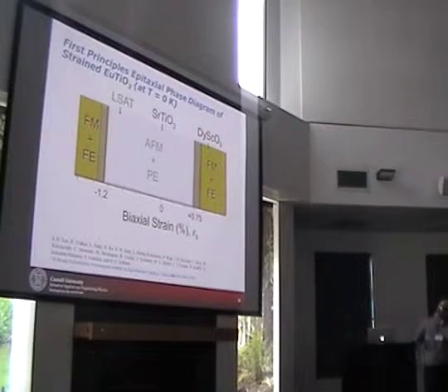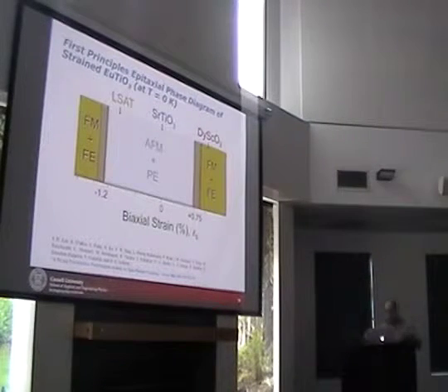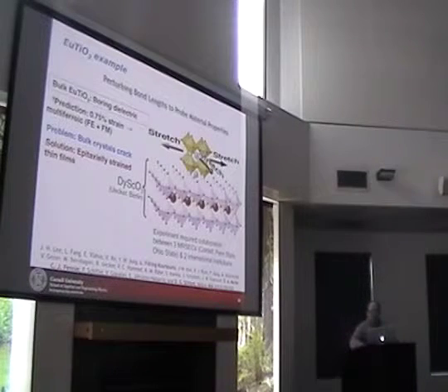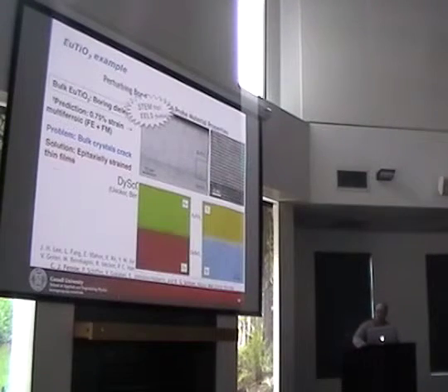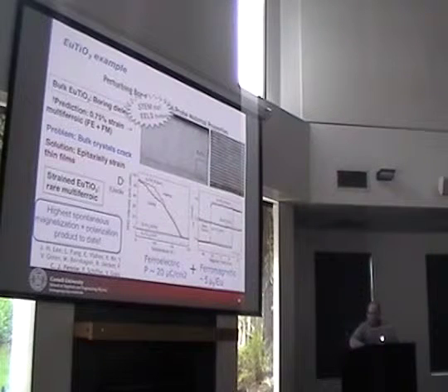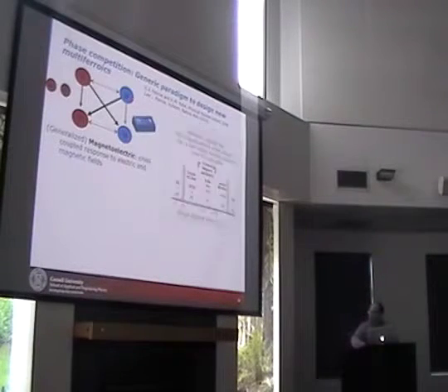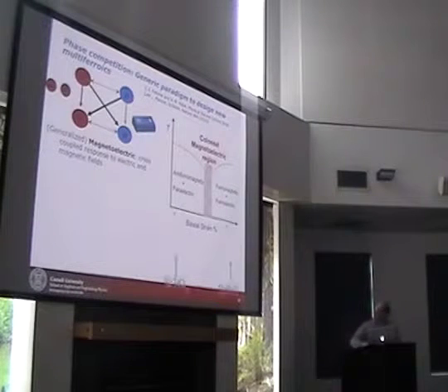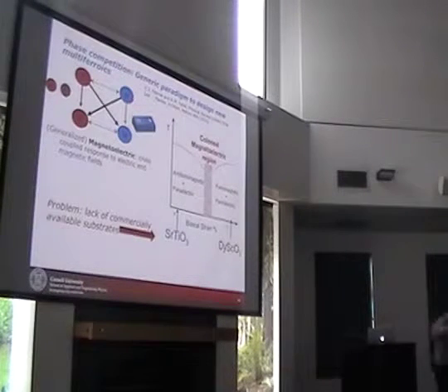The point I want to make is, in fact, my colleague at Cornell, Darrell Schlom, has made this on various substrates, applying these large strains. We make them beautiful films. Again, this is in the interest of time and not really the point. They made them, yes, and we were able to demonstrate that we can control the system. We can take it from its natural antiferromagnetic paraelectric state and drive it with strain into this ferromagnetic ferroelectric state. That's great. This sort of model seems to be working.